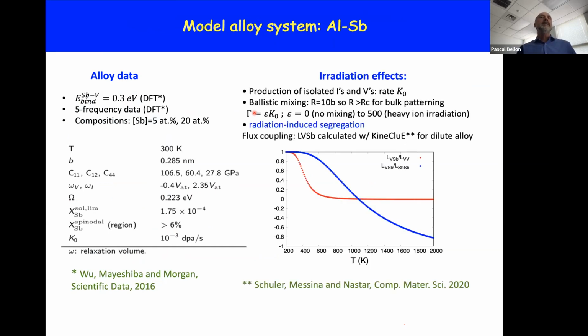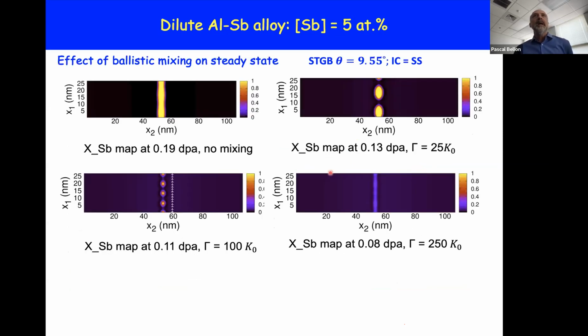We picked aluminum antimony as a model system, in part because we're doing some experiments on this alloy system. It's also one where there is radiation-induced segregation from DFT data. We know that there is a strong binding energy between antimony and vacancy in aluminum, and that leads to flux coupling at low temperature. If you calculate these Onsager coefficients that are presented here using different techniques, what you would see is that at low temperature, if I pick the blue curve or the red curve, it means that every time a vacancy moves through the microstructure, it drags with it one solute atom when this ratio is 1. And so at low temperature, there is a very effective solute drag. And Gabriel looked at microstructures near a grain boundary here with a misorientation angle of about 10 degrees.